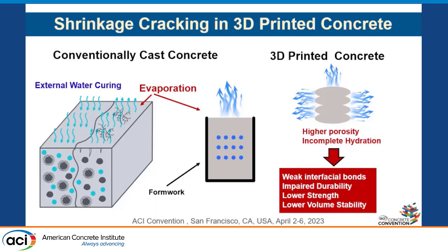Like you see there, in 3D printed concrete there is a risk of evaporation in different directions. This can cause higher porosity, and if the water that is needed for hydration of cement is gone, then we would have incomplete hydration. And then we would have weak interfacial bonds, impaired durability, lower strength, and lower volume stability.